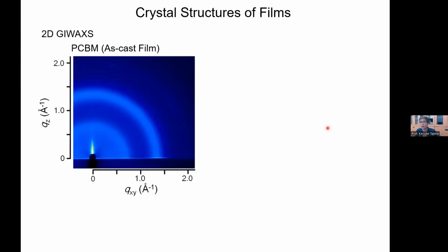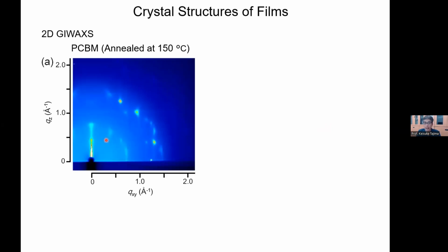What we want to do is control the crystallization process of the PCBM in the bulk. Actually, a lot of people think that PCBM is amorphous, and it's true. As-cast film doesn't show any diffraction peak, just a ring shape, so it's amorphous. But after annealing at a high temperature, say 150, it does crystallize. You can see these spots here, right? So it crystallizes, but it's multicrystalline, the domain size is small, and the orientation of the crystals is not aligned very well. That's what typically happens for the PCBM film.